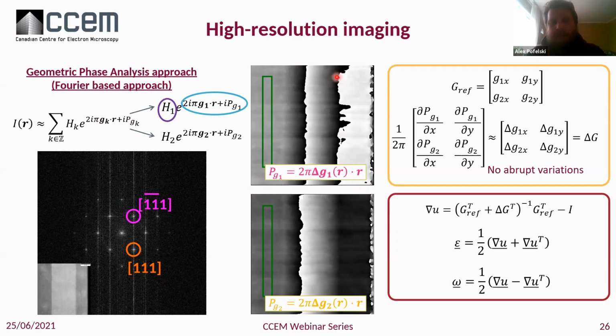So with these two phase images, by taking the gradient of this phase, we have direct access to delta G. So this is again an approximation, because when you do the derivative of this dot product, we don't have directly delta G. There is an approximation. So this is this no abrupt variation hypothesis that is important to have. During the masking process, since we select a certain reference here, we also have the evaluation of the reference G component in the 2D space.